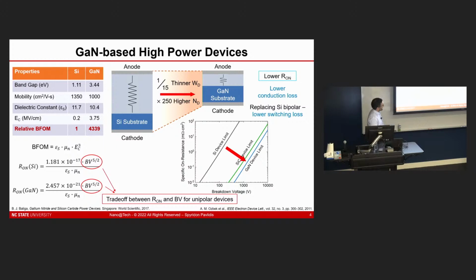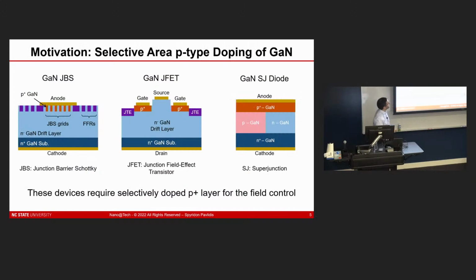But one of the things that I want to highlight here, and this will be especially important when I start talking about the superjunction devices, is that, as noted here, the relationship between breakdown voltage and R-on is pretty fundamental. You scale it by material parameters like the critical electric field, but this slope is basically the same. And so with the superjunction device that I'll talk about later, one of the things we are looking to do is actually bend this curve downwards and get even more efficiency, even lower loss for the same breakdown voltage. So we're trying to go beyond those conventional relationships and rules.